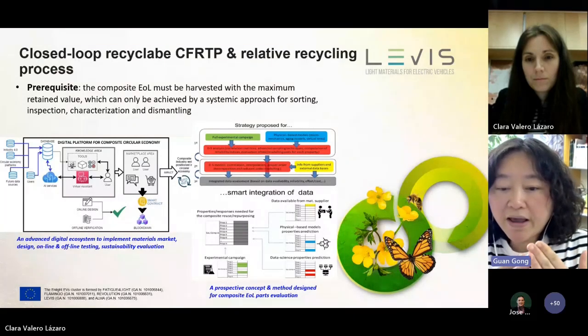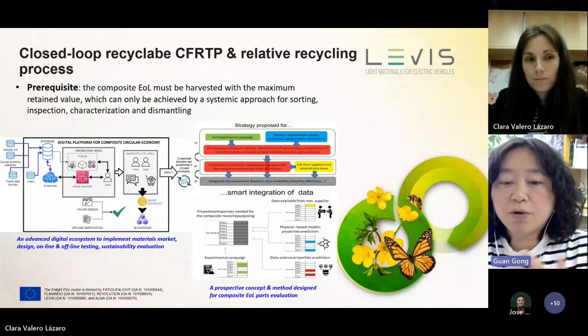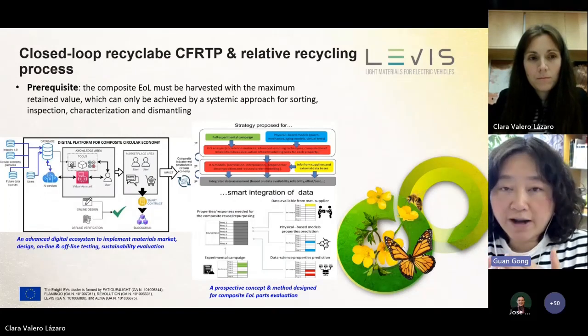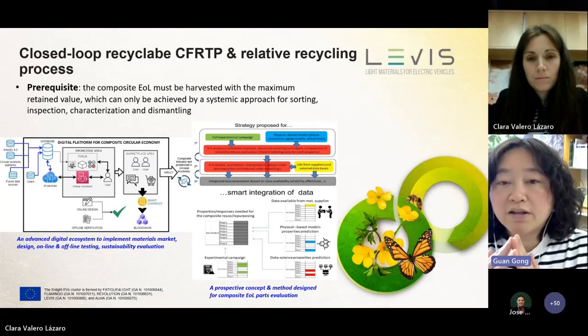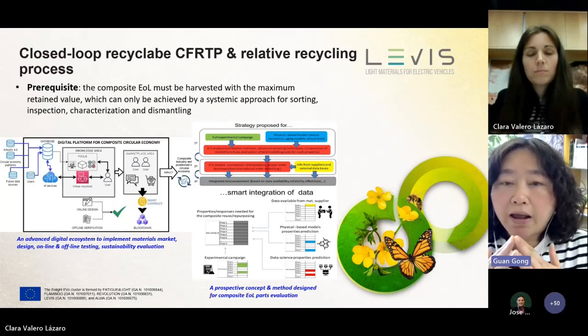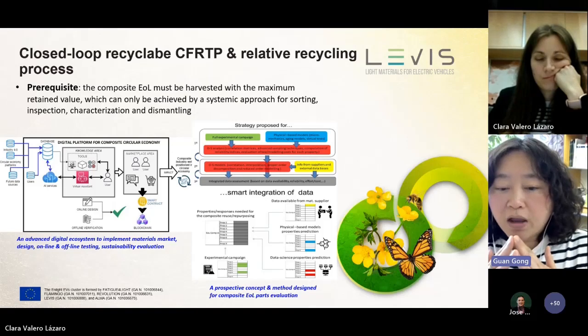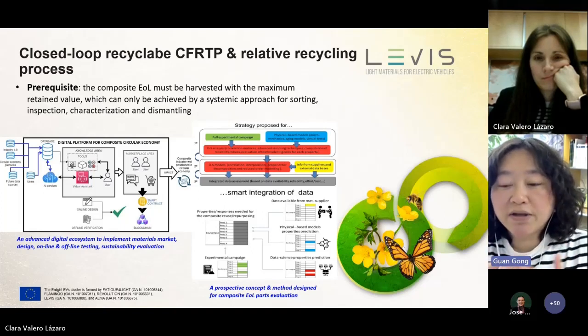For instance, an application can reach its end of life, and the materials contained in it still possess a potential for several more life cycles. Therefore, the evaluation of the overall aging and service status of the composite end-of-life parts indeed has the most significant influence on the reuse efficiency and the quality of the new composite product based on the end-of-life parts. So if the materials in the end-of-life parts are severely aged or degraded, reaching the material's end of life, then the whole composite end-of-life part will not be reliable for reuse in spite of very few or light defects or damaged zones being detected.